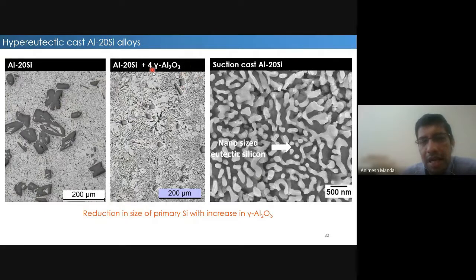Another area we are working on is whether the addition of a low quantity of certain oxides could decrease the size of your primary silicon. And indeed it does, because Al2O3 is a relatively cheap particle reinforcement, and it is quite effective in refining this primary silicon in your hypereutectic aluminum silicon alloy.